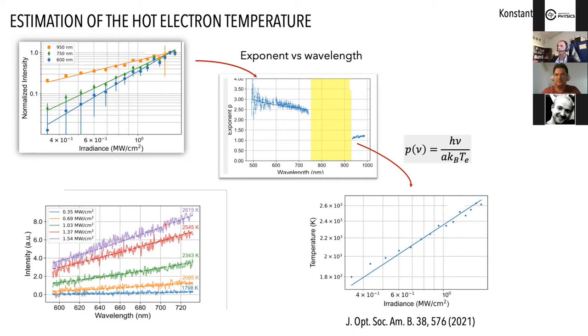The second way of determining the temperature is looking at the power exponent, and fitting this exponent with what is expected from Planck's law. Let me go through these three graphs here. First of all, we take the intensity at a given wavelength. So you take, for instance, 750 nanometers, you change the irradiance of your laser and you fit this curve, you have one exponent. You take another one at 600 nanometers, you have another exponent. And then you plot all these exponents as a function of wavelength.